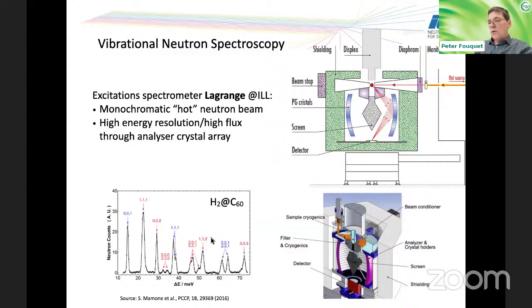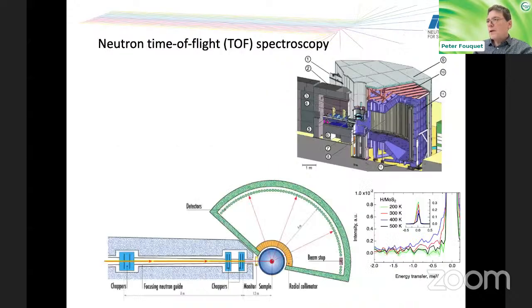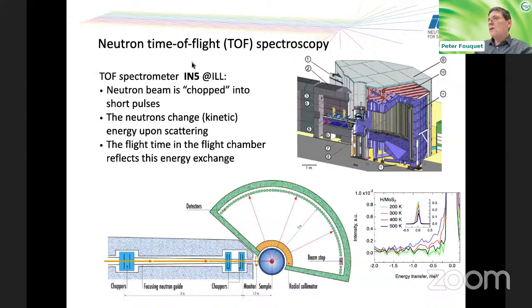And this spectroscopy, of course, covers a similar spectral range as, for example, Raman and infrared spectroscopy. But you can investigate with this samples which are not attackable with Raman or infrared, for example, because they are black and not transparent to light. Now, the second spectroscopy technique that we use very much here at the neutron facilities, that's the time-of-flight spectroscopy. Here I show you a spectrometer, IN5.